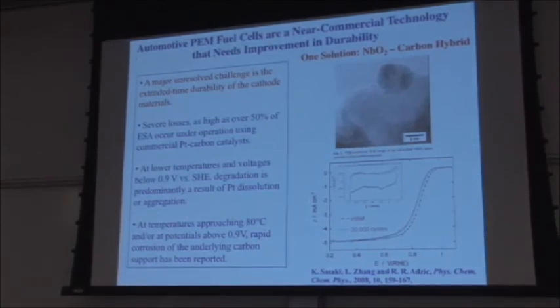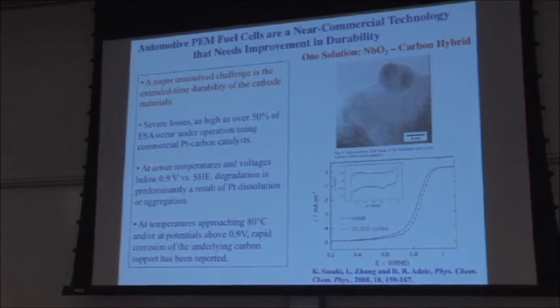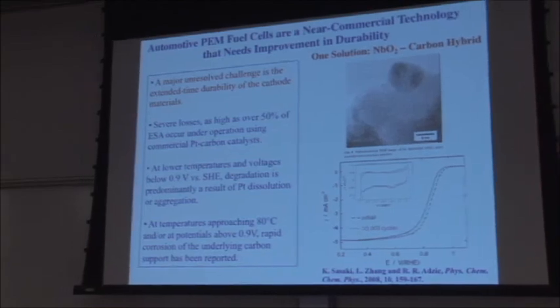So we're starting with a fairly good assumption that PEM fuel cells, which are near commercial technology for automotive applications, need improvement in durability. And a major unresolved challenge is specifically the durability of the cathode. If you look at an operating cathode, especially during start-stop type of operation, you get loss as high as 50% over, let's say, 10,000 cycles of your electrochemical active surface area. And at lower temperatures, this is, people argue, straight up dissolution of the platinum. And of course, that leads not only to the loss of electrochemical surface area, but also to reprecipitation of your platinum in your membrane, which is not that good.